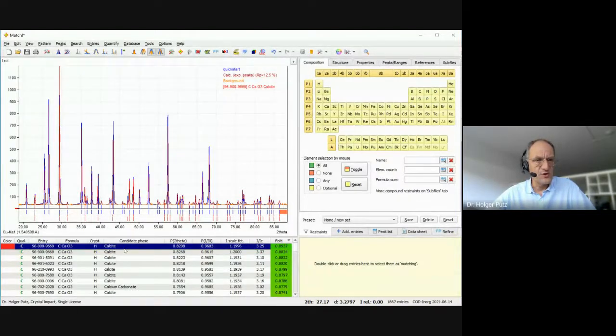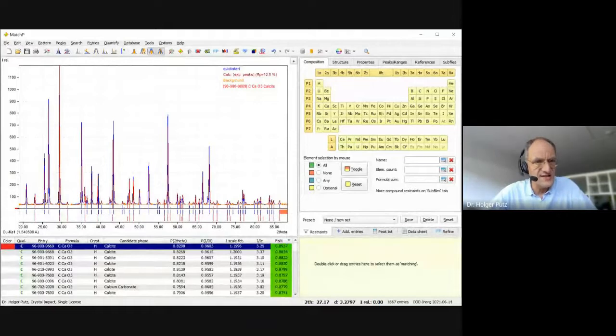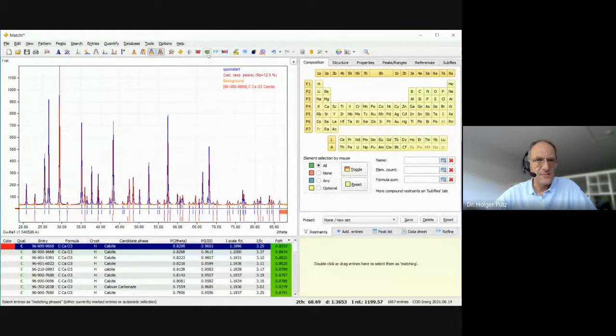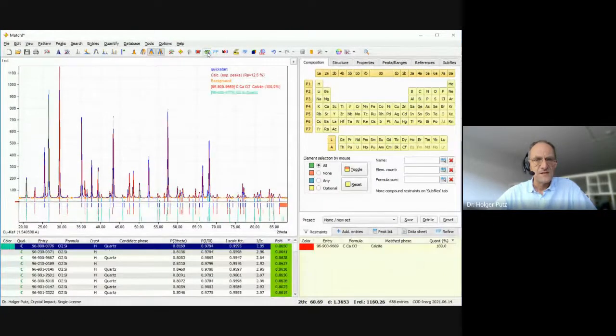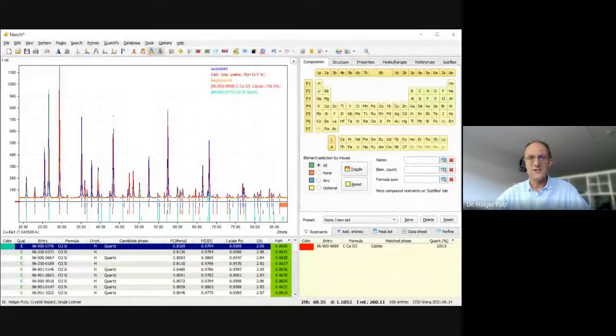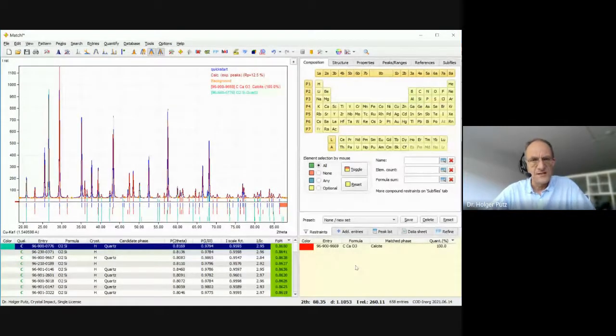So we have our best matching phase, which is calcite in this case, and I can select it as matching, for example, by pressing this button here at the top. Just click on it, and now Match has copied this entry calcite to the match list at the bottom right. That is, I have selected it as matching and decided that this phase should be present in my sample. At the same time, in the background, it has also subtracted the peak intensities that belong to calcite from the experimental peaks and run another search match calculation.